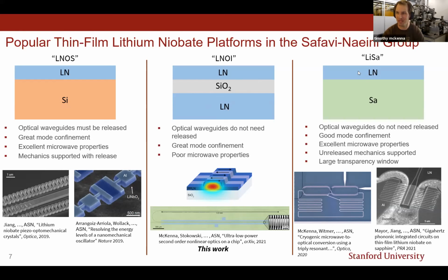Finally, we have this platform that's lithium niobate on sapphire, and this is a fan favorite. So here, the optical waveguides don't need release because sapphire has a lower index than lithium niobate, has good mode confinement, really good microwave properties, and we've used this for low temperature electro-optic microwave experiments. It's also really nice because unreleased mechanics are supported. That's this work here by Felix and Wentao, where they demonstrated photonic integrated circuits on LiSA, we call it LiSA. Also, Chris Sarabalis has made some really impressive unreleased mechanical devices on LiSA as well.